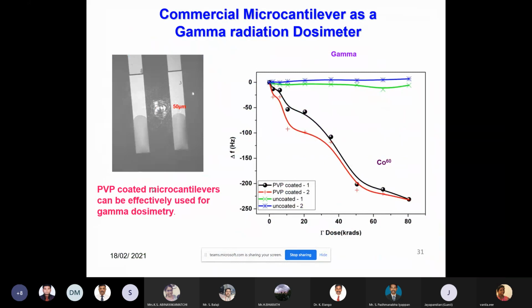This is another, very high radiation. What we did: the commercial cantilevers, both identical, were dipped in a PVP coating. We tried different polymers, but the PVP polymer alone shows fantastic results. Here the blue and green graphs are without any exposure; we leave them for some time. Without coating, we exposed up to 100 kilorad, and the cantilever doesn't exhibit any variation. Then we coated with PVP. Here you can see both are identical cantilevers, black and red being the two cantilevers.